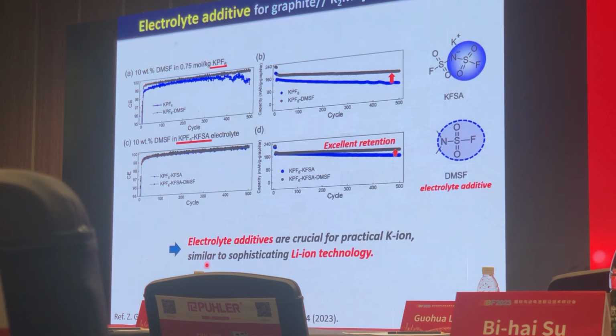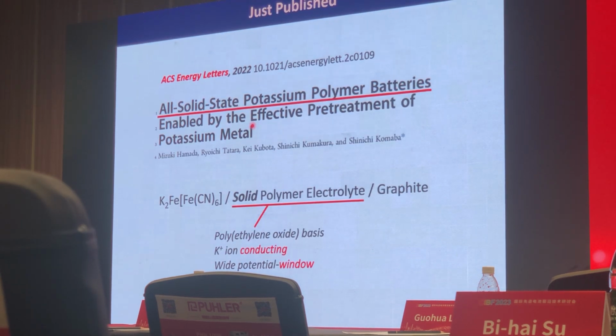So let me introduce the first one, an electrolyte for SEI formation. As a chemical analog of the FSA anion, with two methyl groups, the DMSF additive was successfully found to be a quite efficient electrolyte additive for potassium ion batteries. And by adding DMSF, capacity retention is highly improved, with higher coulombic efficiency over 100 cycles, 500 cycles. Also, we recently reported all-solid-state potassium ion polymer batteries based on polyethylene oxide potassium ion conducting polymers, which show a wide potential window to match with graphite and iron hexacyanoferrate positive electrode cells.